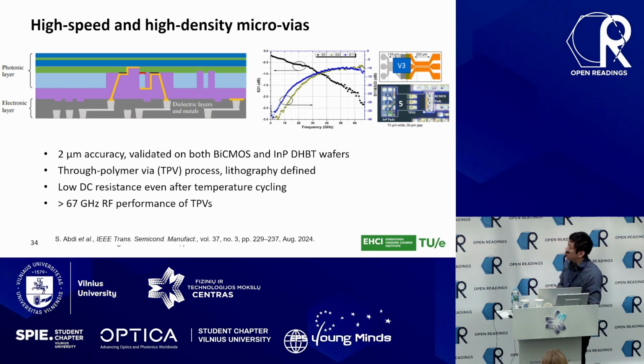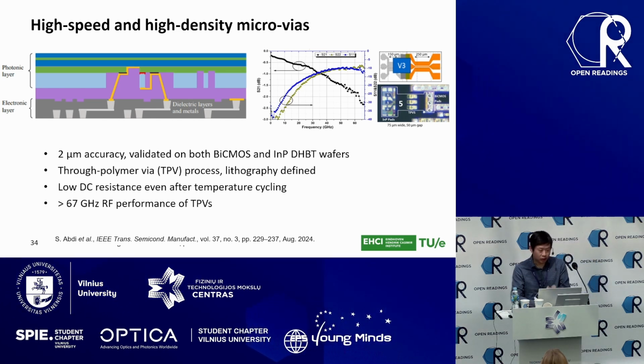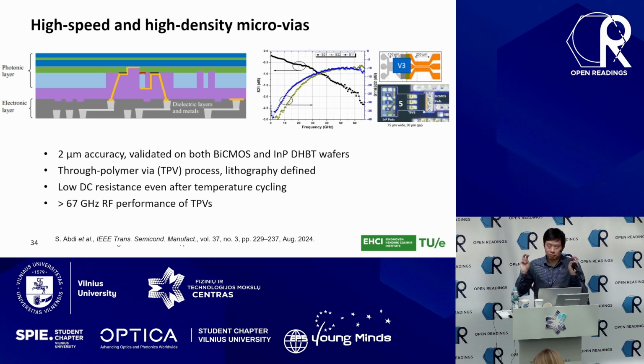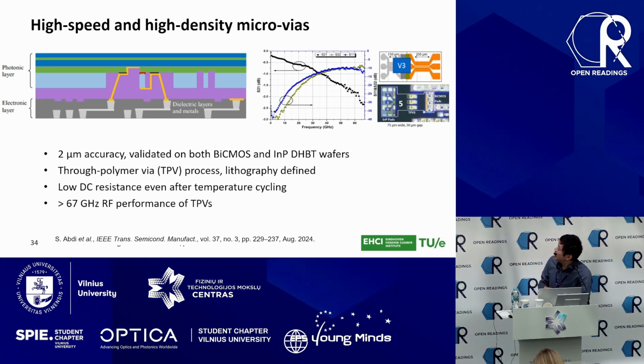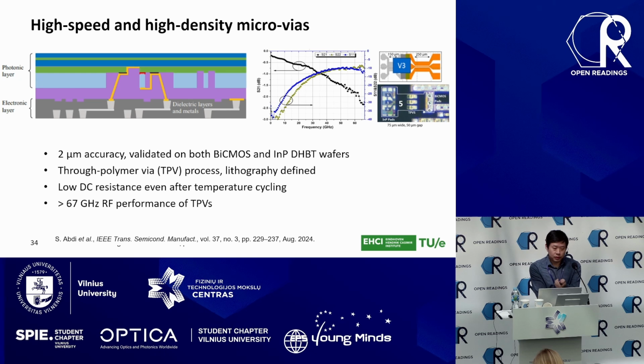We call it through polymer vias, because in this integration, we are gluing the photonic wafer with the electronic wafer with an intermediate glue in between. And this is a polymer. So as you can see on the left side, after the integration, we can drill holes through the polymer, and then expose the electrodes from the photonic side and the electronic side, and then make the connection. And on the right side, we characterize the performance of such vias.